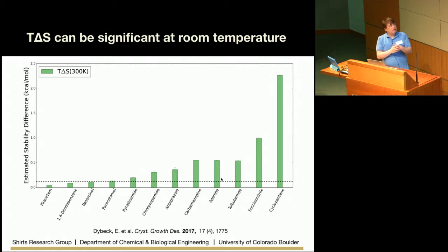And so you do have to worry if you find any polymorph that is measurably more stable, or even one that's less stable. Just because you crystallize something doesn't mean it's the most stable. It could be relatively high, half a kcal per mole or more in free energy, but will be very kinetically stable. So you have to worry about all of these small differences and the existence of polymorphs with these small differences. So generally, using some criteria that other people have used, at least 2/3 of these have entropic differences that need to be taken into account, so that a pure lattice prediction would not get these right.